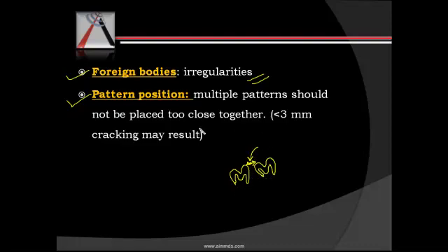If these two wax patterns are placed too close together, there may be cracking seen in the investment between the two wax patterns. So if the space is less than 3 millimeters, the chances of cracking are high.